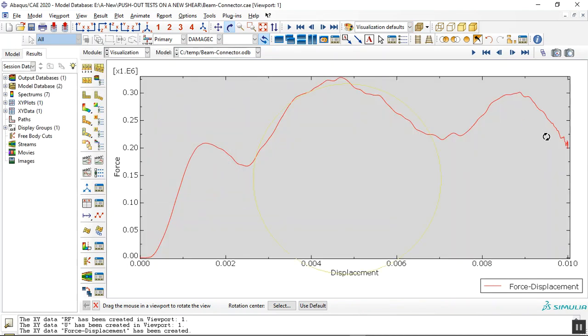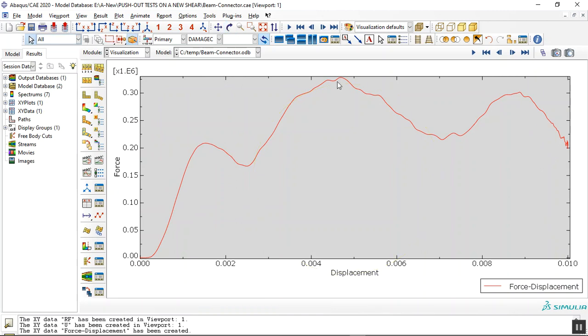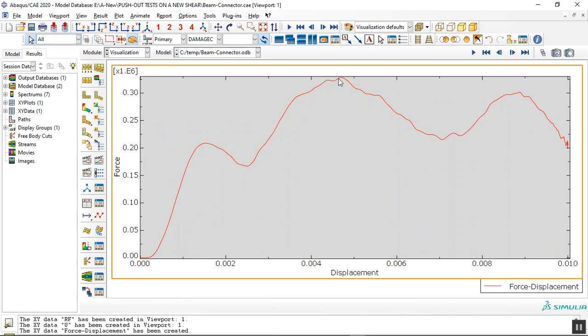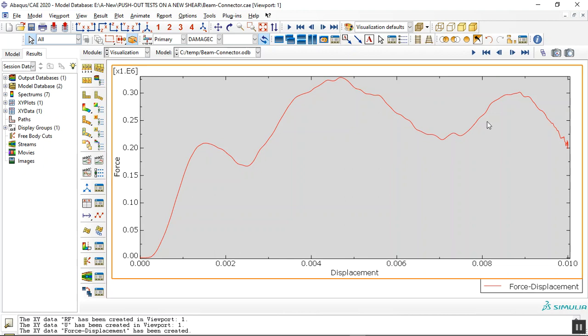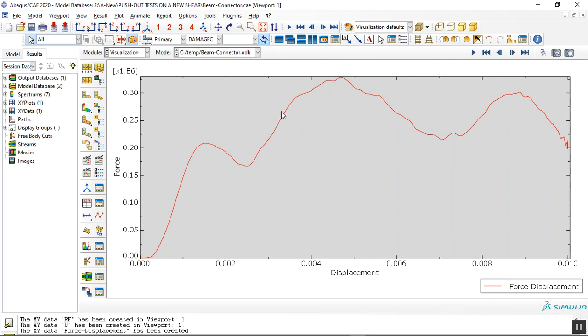Till that displacement 10 millimeter, the maximum happened around 0.35 mega newton, and after that we have decreasing capacity. And you can see the diagram is not the smooth diagram because of the shear connector effect and the interaction between the steel beam and the concrete. You will have some peaks, but this is the main peak here. We can consider a line like this for it.